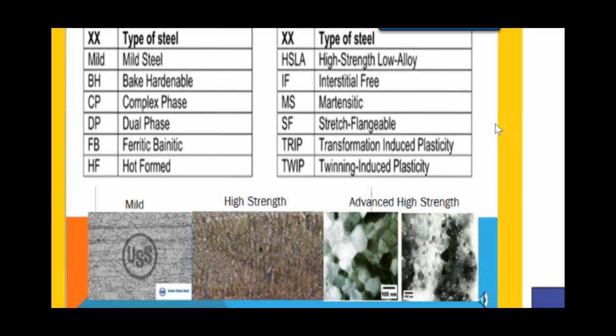You know, when I started working on vehicles, they were all this mild steel. And if you look at that picture under microscope, you can see the grain structures, what that's showing. And the grain structure is kind of spread apart. So for mild steel to get strong, it needs bulk, thickness. One of the ways that we measure the strength of steel is a yield test. So if you were to take that piece of mild steel, grab onto it on each side and pull it apart, it would take approximately 30,000 pounds of pressure to pull that piece of steel apart. Now that sounds like a lot of pressure. But now we're dealing with bulk.